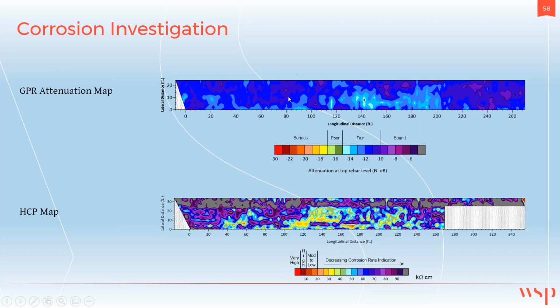This first map here is the GPR attenuation map for a bridge deck, and the second map is the corresponding half cell potential map. We see that the areas GPR identifies as having higher attenuation also appear to have higher probability of active corrosion as identified by half cell potential. As always, NDE results need to be validated using some ground truth information.